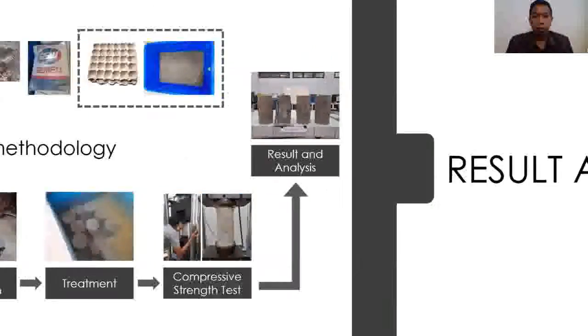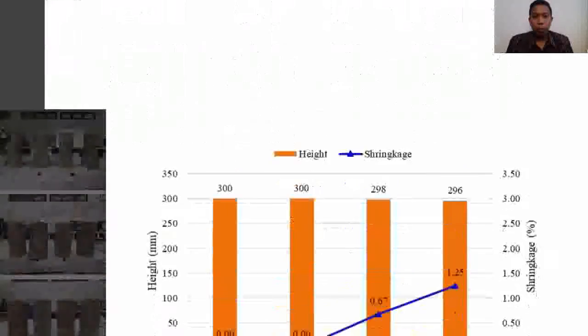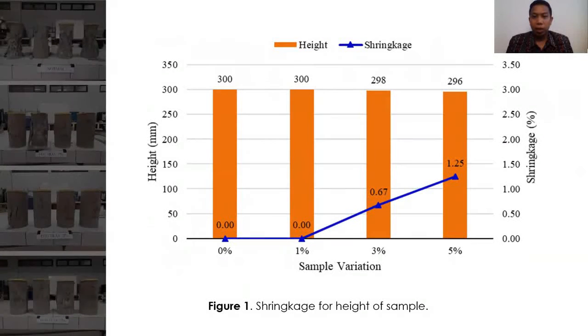Result and discussion. The specimen produced from each variation of the egg tray percentage as a substitute for sand in the concrete mixture shows different volume of test specimen within 24 hours after being poured into the mold, as shown in figure 1. In normal concrete specimen and 1% egg tray percentage variation, there is no change in the specimen height, which is still according to the existing mold of 300 mm.